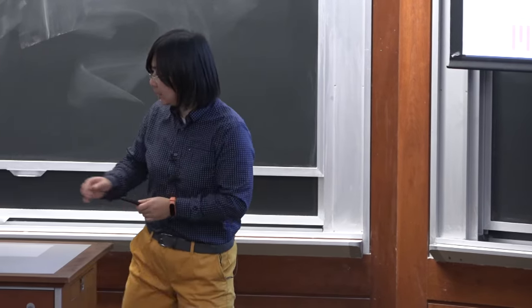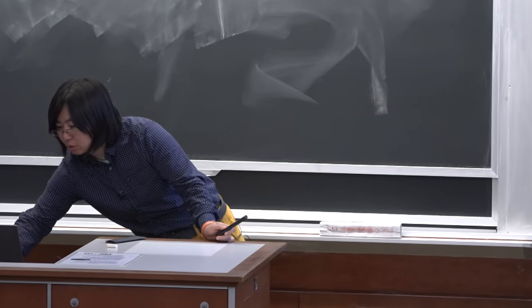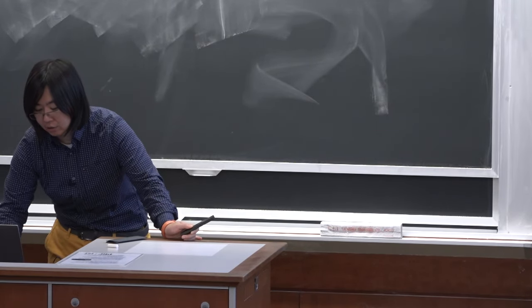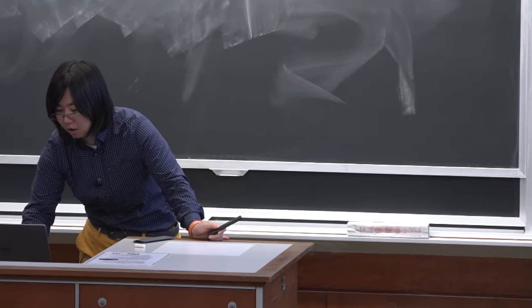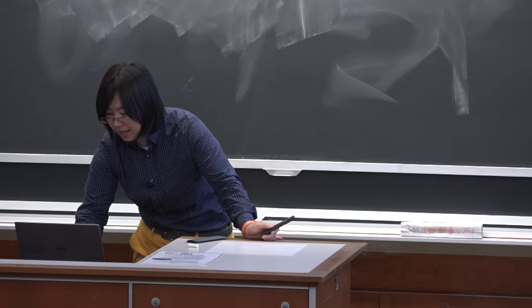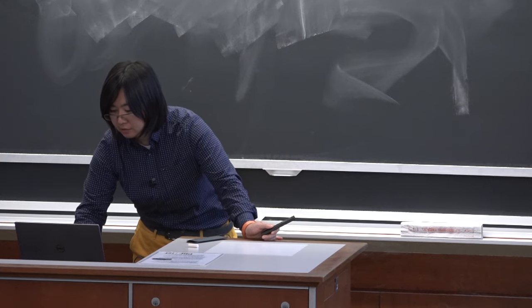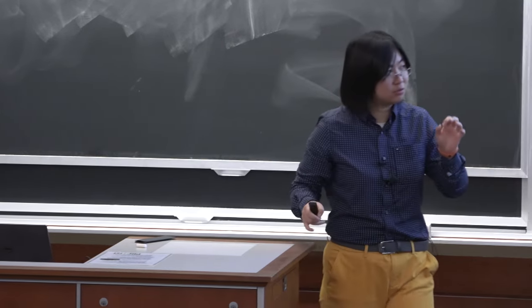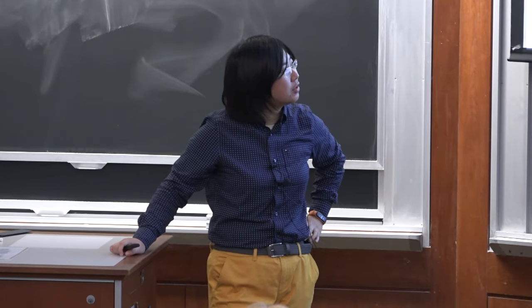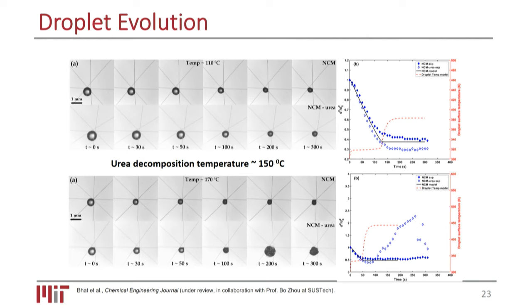I can show you the slides, but the quick answer is that it also depends on the concentration of the solute you have inside the droplet. Since we didn't use a really high concentration, well, high is relative, and it's not that we are fitting it to the data, it's just how the data shows. I would say it's a pretty linear relationship there. It's not that we presumed a D square law; by looking at the data, we think the D square law can explain it relatively well.